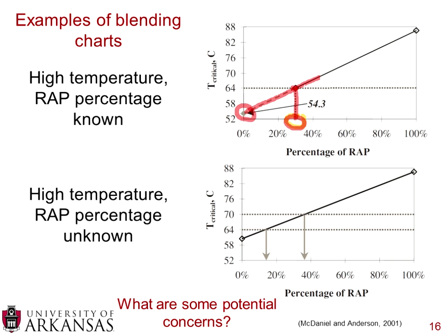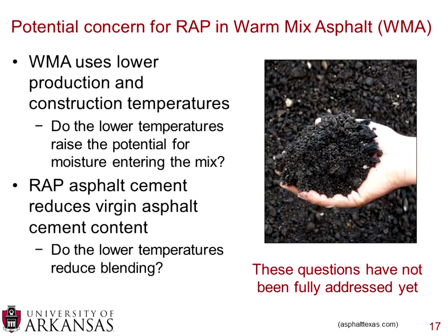And if your RAP percentage is unknown, you can look at either your 64 or your 70, and you can get right here a range of the percentage of RAP that you expect to see in that mix. So there's two ways of dealing with this RAP. You can either use a blending chart when you know the percentage of RAP, or if you do not know the percentage of RAP. And these blending charts are available for high temperatures, intermediate temperatures, and lower temperatures.